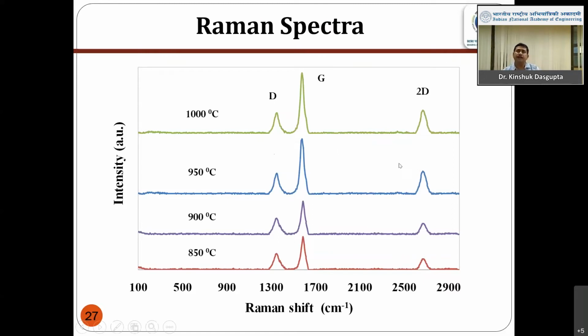Typically, carbon nanotubes have three characteristic peaks: one is called D, another G, another 2D. If it is multi-walled carbon nanotube, you will get a slightly high D peak, but in the case of single wall carbon nanotube, there should not be any D peak. I'll show this in the subsequent slide. The D peak is not there; rather there will be another peak called the RBM peak. So by seeing the peaks, we can tell if this is a single wall carbon nanotube or amorphous carbon. In the case of amorphous carbon, the D peak will be higher than the G peak. So if D is higher than G, we can tell this is not carbon nanotube at all.